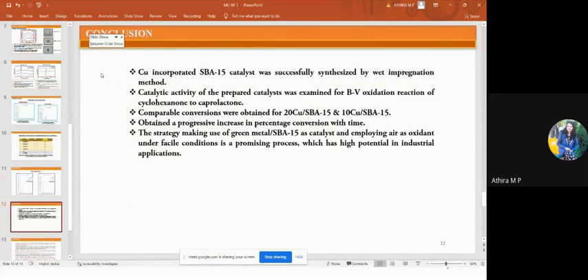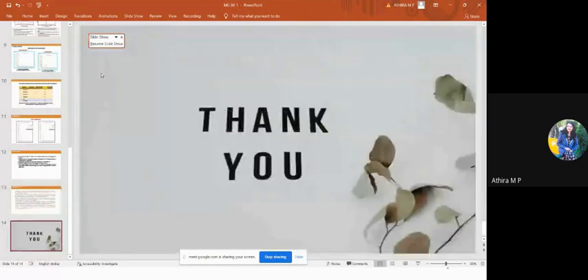In conclusion, copper incorporated SBA-15 catalyst was successfully synthesized by a wet impregnation method, and the catalytic activity of the prepared catalyst was examined for the BV oxidation of cyclohexanone to caprolactone. Comparable conversions were obtained for 20 copper SBA-15 and 10 copper SBA-15, with a progressive increase in percentage conversion with time. This strategy, using green metal SBA-15 as catalyst and air as oxidant under feasible conditions, is a promising process with high potential in industrial application. These are some references. Thank you.